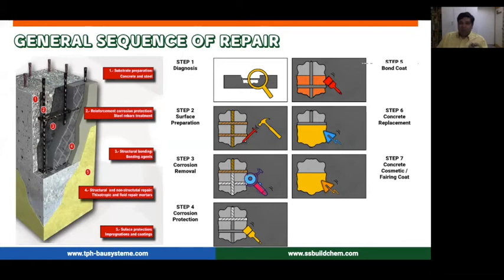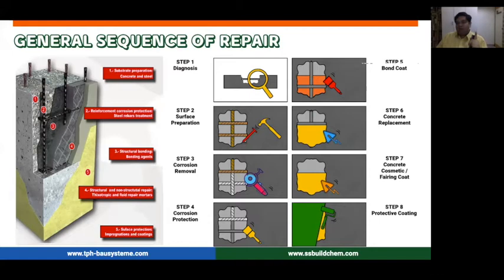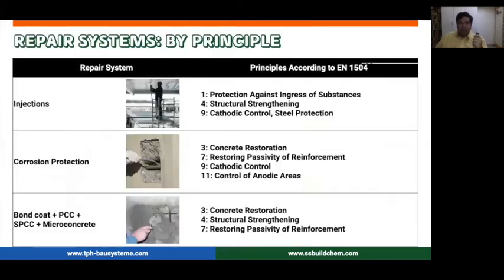Then you have a concrete cosmetic fairing coat, just to give an even surface for your protective coating systems. And last but not least, once the repair is done, you have to protect your structure, because if you do all the very difficult steps of repair and you leave your structure unprotected, then your repair cycle is just going to repeat, maybe within the coming year. So a failure of repairs becomes a big problem, and it can only be remedied by protecting our structure properly.